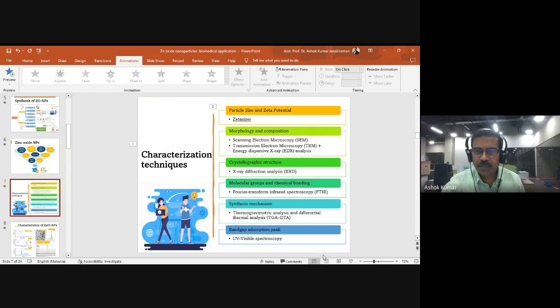We can have coupled TEM and EDX, which is used for the chemical composition and mapping of zinc oxide. We can do it individually or merge both TEM with EDX. And XRD, of course, is to confirm the crystallinity of nanoparticles. So the crystallinity of nanoparticles is confirmed by using X-ray diffraction, and for the molecular groups and chemical bonding, of course, by using FTIR, and the decomposition behavior we will confirm by thermogravimetric analysis or differential thermal analysis.